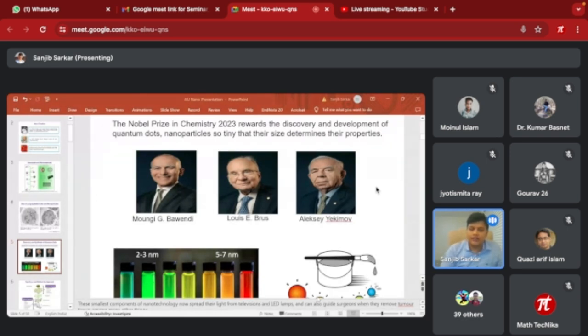And if the quantum dot size is less, like 2 to 3 nanometer, then it can emit blue or green light. And when the size is increasing, like 5 to 7 nanometer, these nanoparticles give yellow to orange, then red color. So the size of the nanoparticles matters.